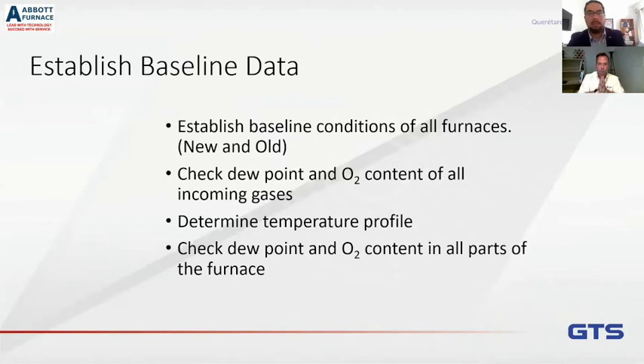So again, when everything is working, do an atmosphere profile, so you know what that atmosphere composition should be throughout your system. Check the dew point and oxygen at all of the incoming gas as well. That's one of the first things: when you go to do an atmosphere profile, always start at your incoming gases to make sure that you're not feeding garbage in and getting garbage out, right?